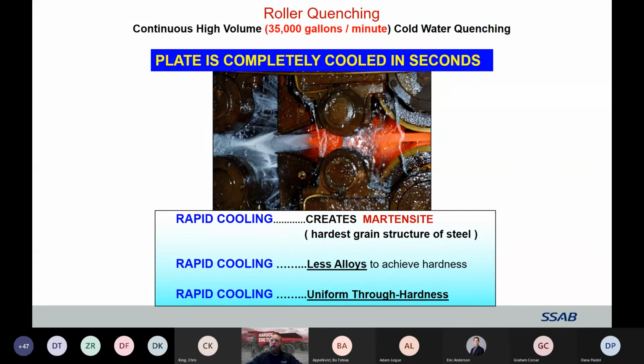Now, our quench is what we call a roller quench. So we use around 35,000 gallons of water per minute, and the water is actually monitored for chemistry and temperature. We want to make sure that the water is consistent to completely cool that plate within seconds. And we can actually quench a plate from 900 degrees C down to less than 50 degrees C in under a minute, and that's even for a 1-inch thick plate.